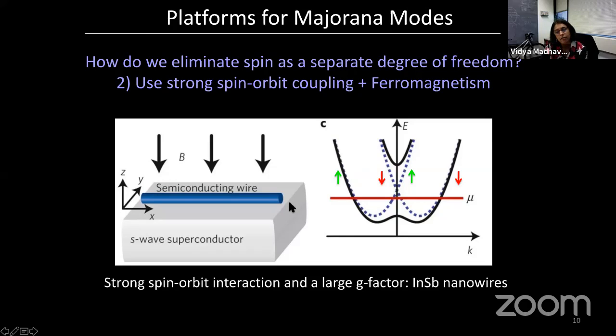And now let's turn on a magnetic field or have magnetic impurities such that at the crossing point, you develop a gap. Typically this is done for these semiconducting wires by turning on a small magnetic field. Then you want to place, by gating or some other technique, your Fermi energy in this magnetic gap, and then proximatize the system with a superconductor. If you are able to engineer such a system, then because of the band structure, first, there's only one band crossing the Fermi energy. And second, due to strong spin-orbit coupling, the spin of each electron is locked to its momentum. So you've naturally eliminated spin as a separate degree of freedom.